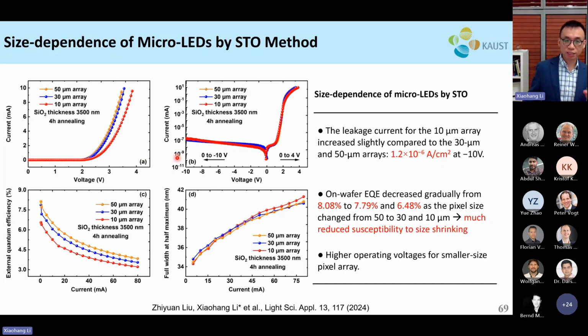And then we also look at the size dependence, because we want to see how the size dependence may change with the selective thermal annealing method. So here we found that we still have some size-dependent effect. Okay, and then the on-wafer EQE decreases gradually from about 7.8% to about 6.5% when we change the pixel size from about 50 to 10 micrometer. However, by comparing with literature, we notice that the size effect has been much reduced. That means this technology provides a much reduced susceptibility to size shrinking in terms of the external quantum efficiency.